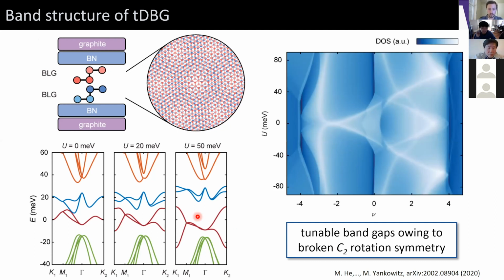Now we can calculate the density of states from this band structure as a function of the doping, or what I'll call the filling factor, roughly analogous to the language of some sort of degenerate quantum Hall system, where each one of these bands is fourfold degenerate for 2 spin and 2 valley degrees of freedom. So full filling now is what I'll call nu equals 4. That's when the chemical potential has completely filled the conduction or valence bands. And when we calculate the density of states, of course, it's consistent with these band structure calculations. We see the density of states vanishes at high displacement fields at the neutrality point. It vanishes at full filling and then actually becomes semi-metal again at high displacement field. And then we also see these regions of high density of states corresponding to Van Hove singularities and band edges within these flat valence and conduction bands. And these disperse with electric field in certain characteristic ways.